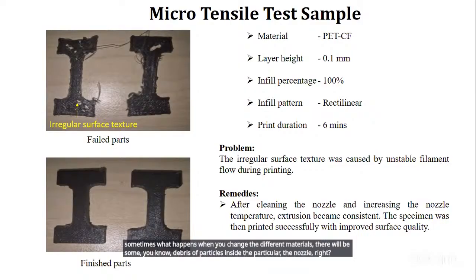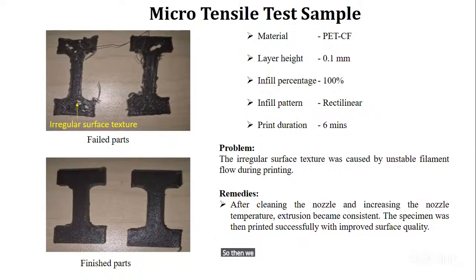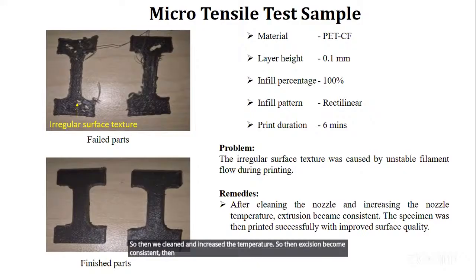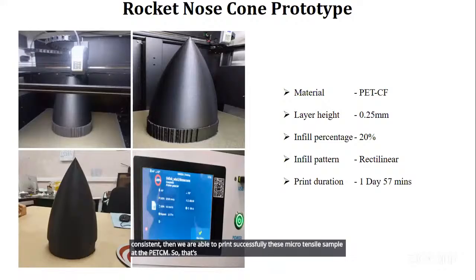We had used PET-CF to print it, so those carbon fiber particles were there inside the nozzle. Then we cleaned it and increased the temperature, so then extrusion became consistent. Then we were able to print these micro tensile samples of the PETCF successfully. So that's how we have tried it.